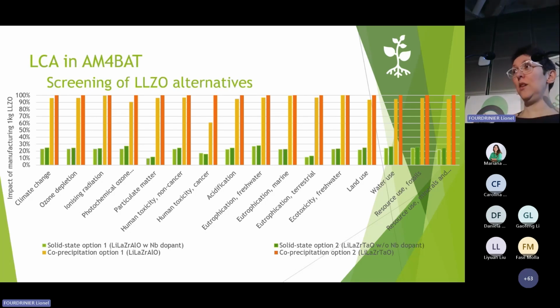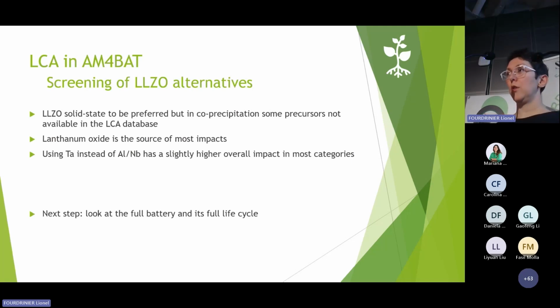This is why LCA is really important, because with the same material, we can see that different process alternatives lead to completely different results. Here we can see that the solid state option is probably the best, and using aluminium instead of tantalum can also be quite useful. However, in LCA we are using some databases, and we still have to confirm the results because we still have to model some precursors, particularly for co-precipitation. In most of the impacts that I've shown, in fact, lanthanum oxide was a main hotspot. And as I said, tantalum has a higher impact than aluminium or niobium. As LCA concerns the life cycle, the next step will be to look at the full battery and the full life cycle.